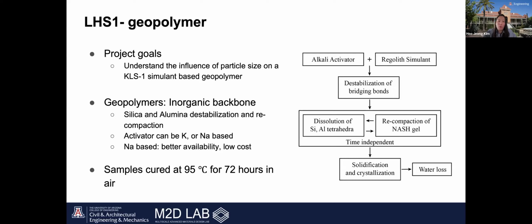And as water evaporates, the silica and alumina organize into the amorphous gel known as NASH, or sodium aluminosilicate hydrate, and the material reaches its full strength once this gel is fully dehydrated and solidified. For lunar applications, the precursor powder would come from lunar regolith, while the sodium activator would either be brought from Earth or extracted directly from the regolith itself.